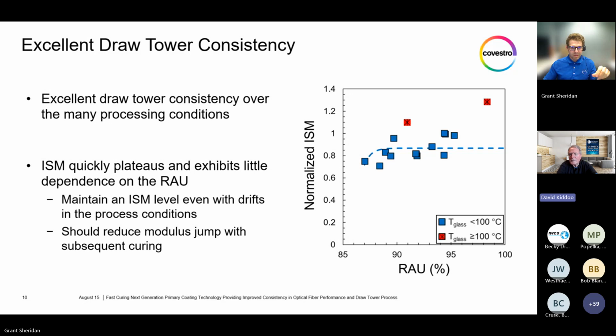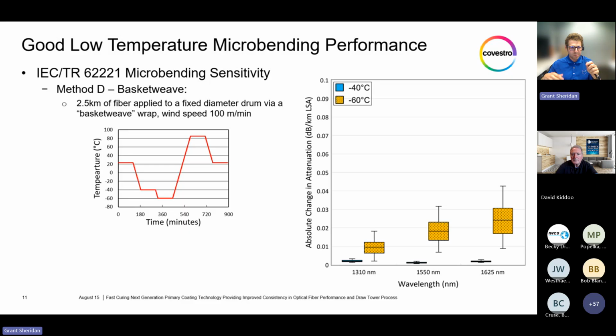Good. And what was the final coating diameter for the microbending test? Will the new coating still perform well in terms of microbending loss if the coating diameter is reduced, for example, to 200 micron or 160 micron? Yeah, so this is 250, and that's the new aspect of the new branch. We're branching out to multi-mode or thinner coating levels, and we would anticipate a similar microbending performance at that level, due to being able to push the glass transition temperature, the Tg, of these lower. But we're still exploring that and expanding to thinner fiber at the moment.